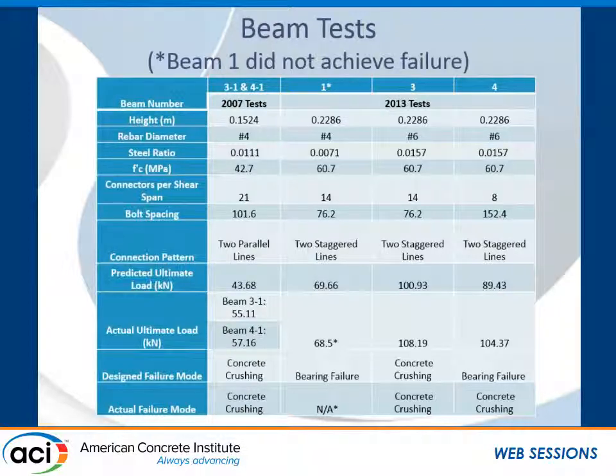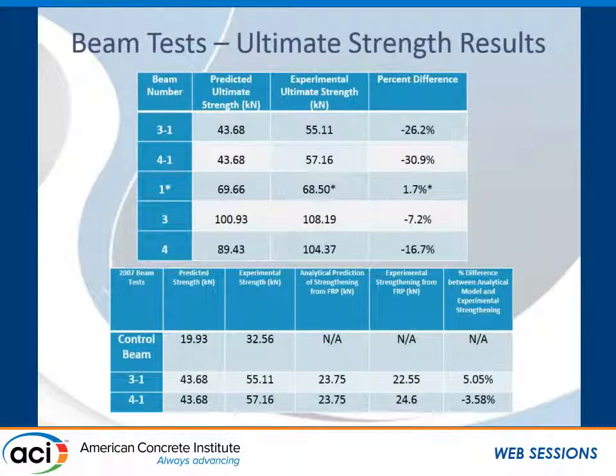than the prediction. If you contrast that with beam 3 on the slide, which was very similar but with a different connection pattern and predicted to fail by concrete crushing, that is the failure mode we got there, and the difference in the prediction was only 7%. So contrasting the behaviors of those two beams, we get the sense that the achievement of predicted failure mode affects accuracy of our ultimate strength prediction. We also looked at, these tables again show comparison of experimental strengths to analytical results.